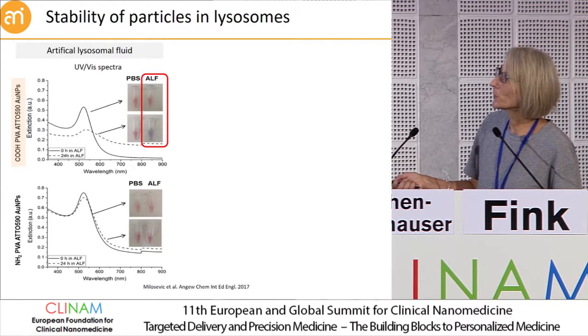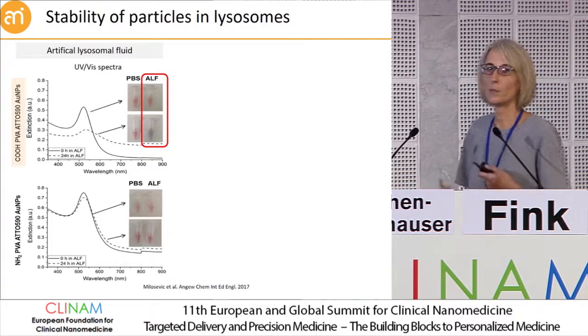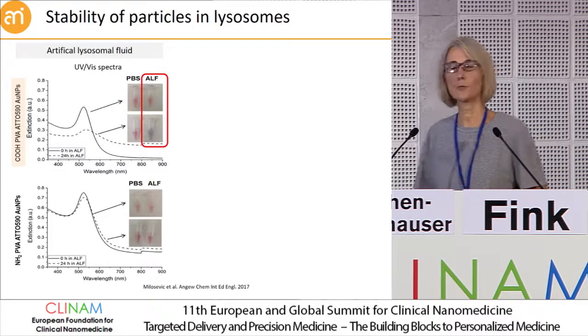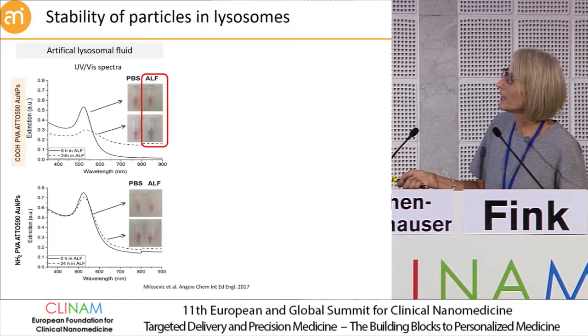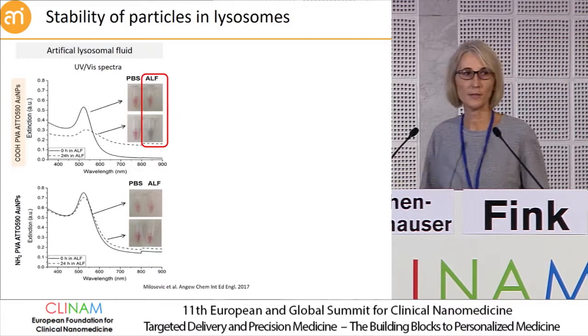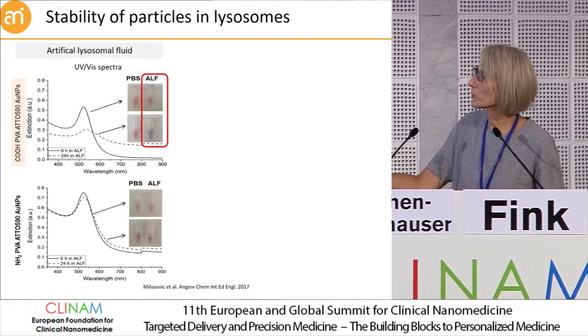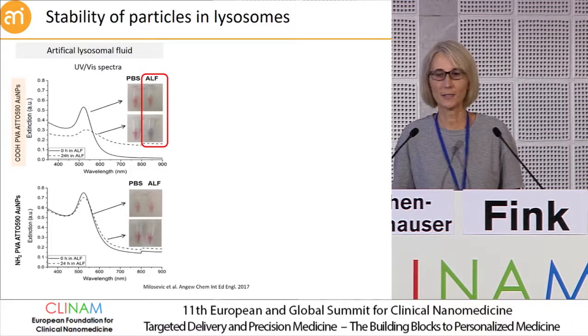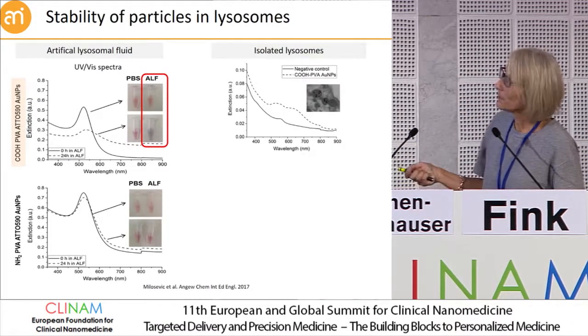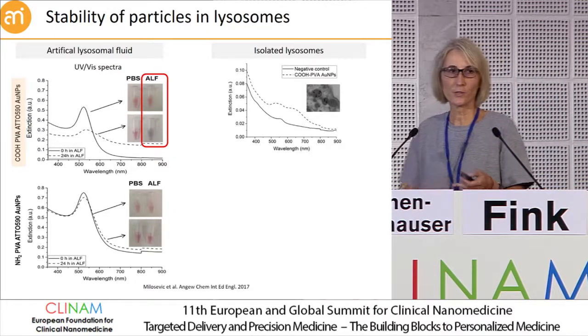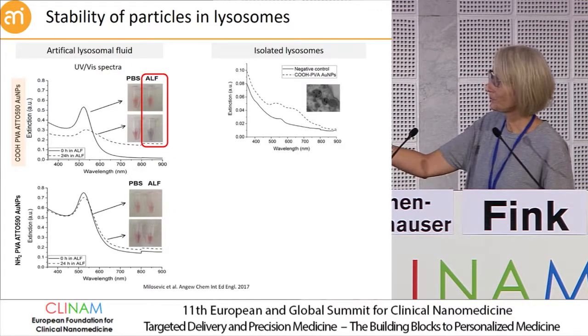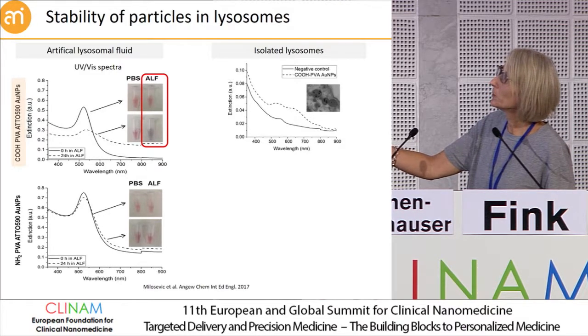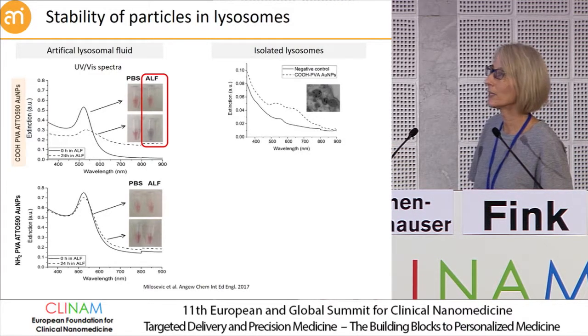And what we observed was that in this artificial lysosomal fluid, by UV spectroscopy, the particles agglomerated. You see a broadening of the spectra, and also by eye we saw an agglomeration of the particles, which we could not observe in PBS buffer, and we also did not see this for the positively charged particles. We did another experiment where we isolated the lysosomes after the cells have been incubated with the particles. And again, we have seen an agglomeration of these negatively charged particles in this acidic environment, but only the negatively